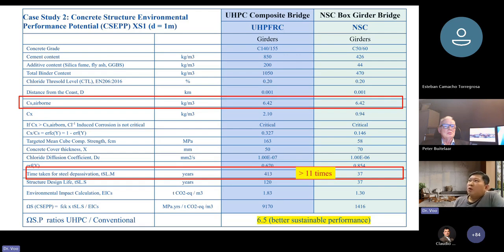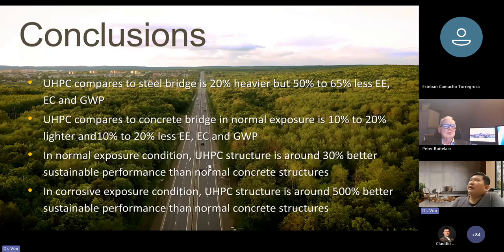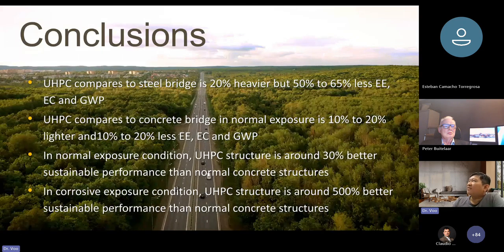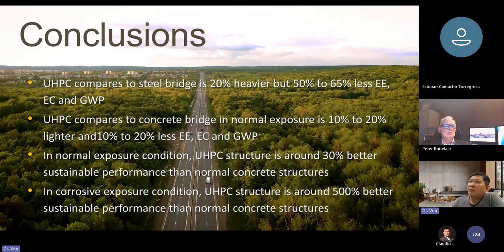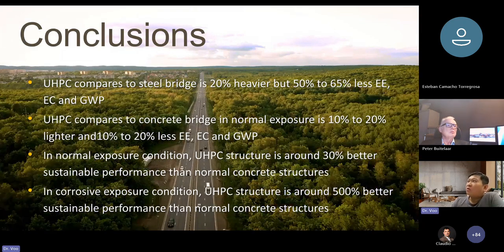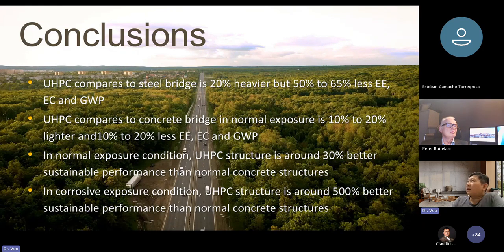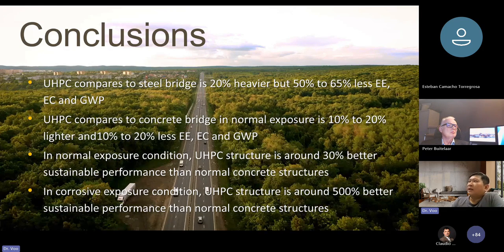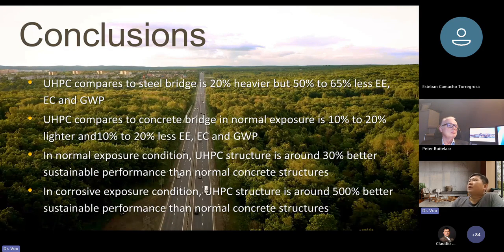So my conclusion is UHPC compared to steel bridge is 20% heavier, but at least 50 to 65% less embodied energy and embodied carbon. UHPC compared to normal concrete bridge in normal exposure is around 10 to 20% lighter and has 10% to 20% less embodied energy and embodied carbon. In normal exposure conditions, UHPC structures have around 30% better sustainable performance than normal concrete structures. But in highly corrosive exposure conditions, UHPC structures have around 500% better sustainable performance than normal concrete structures. Thank you.